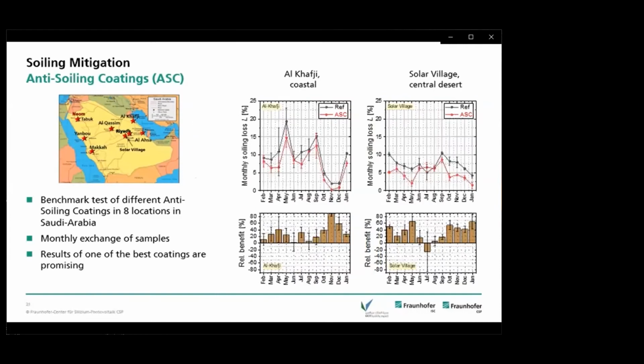On this slide, you can see some results of one of the best coatings, here for 2 different locations. One is Al-Kafji, which is more coastal area, close to the Persian Gulf, and Solar Village, which is close to Riyadh in the central desert. And you can see that the anti-soiling coating, which is the red line, has less soiling in most of the months compared to the uncoated reference.